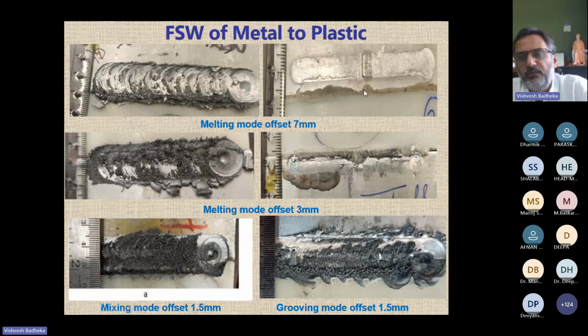You are not putting the tool in because your pin diameter is 6 millimeter. Your pin diameter is 6 millimeter, and you are not even at half of the pin diameter, right? You are at 7 millimeter. Then half of the pin diameter is 3 millimeter. You can see there is a good amount of mixing between metal and plastics. And the third one is called mixing mode. You can see the offset has further gone down to 1.5. Starting from an offset of 7 millimeter to 3 millimeter to 1.5 millimeter. Now you see this is 1.5.